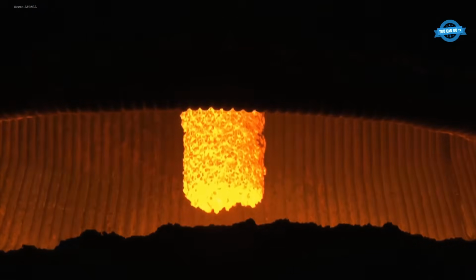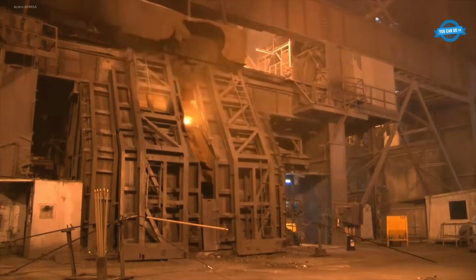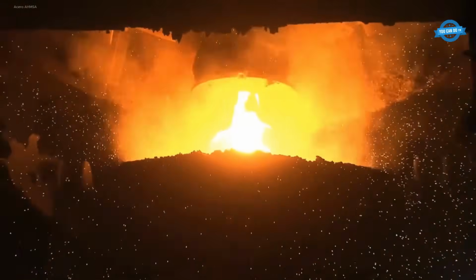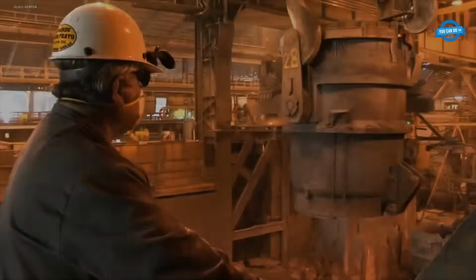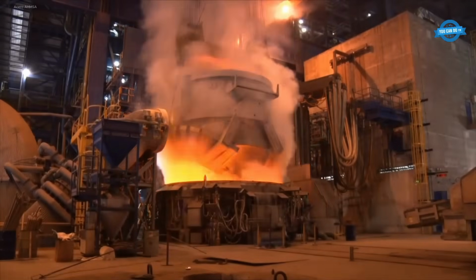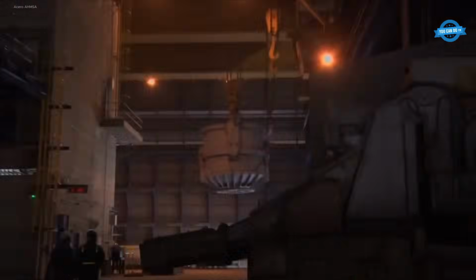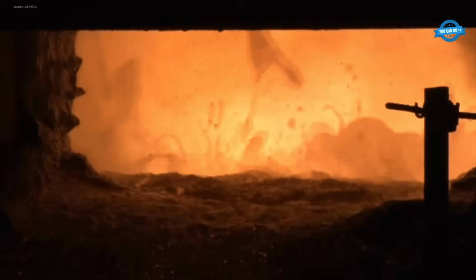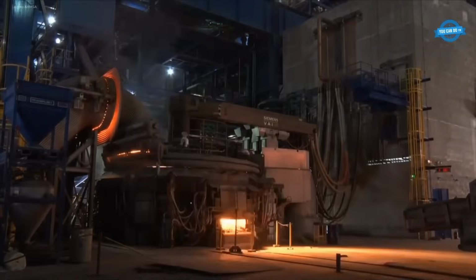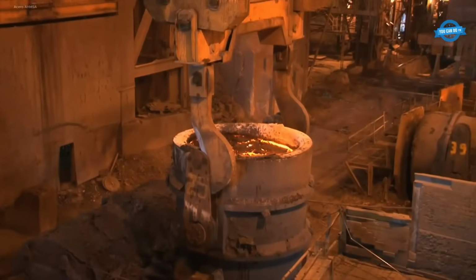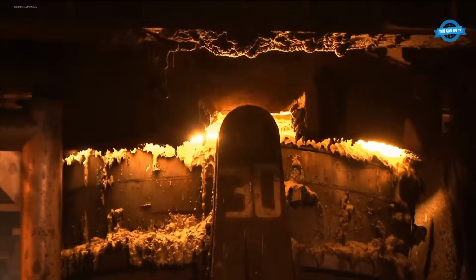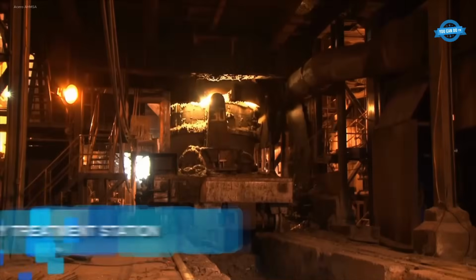In the blast furnace, alternating layers of pellets, coke, limestone, and dolomite are charged from the top. Hot air is injected at the base under pressure, creating temperatures up to 1,650 degrees Celsius. This reduces the iron ore into molten pig iron, which is collected in torpedo ladles. Sulfur content is removed using calcium carbide and magnesium reagents, while slag is cooled and stored as a byproduct.